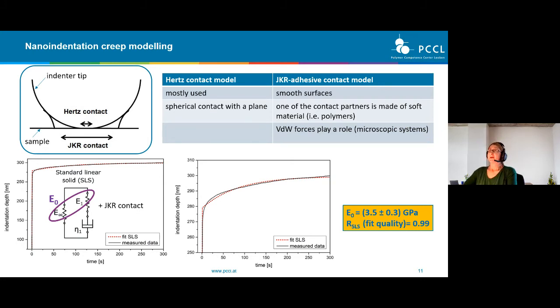So for modeling the PMMA, as you can see down here, we used the SLS model together with the JKR contact. And with this modeling, we got an R value, which is the fit quality, of 0.99, which is quite high, and an E0, so an elastic modulus, of 3.5 gigapascal.